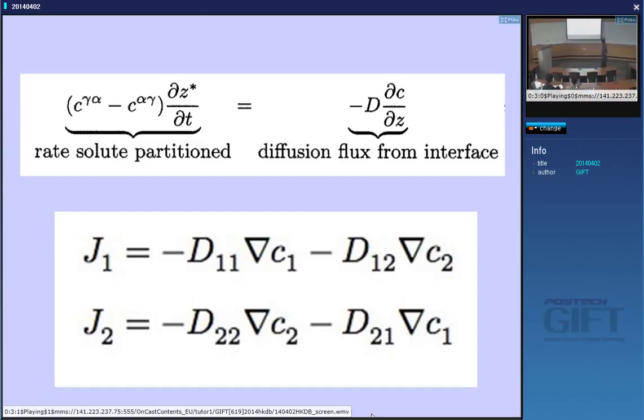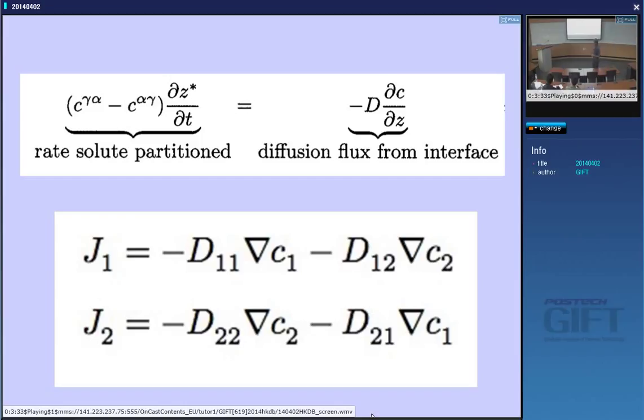The concentration terms in the phase diagram for manganese and carbon are different, but not eight orders of magnitude different. The concentrations of carbon and manganese which are in equilibrium in the phase diagram are not eight orders of magnitude different, and similarly the gradients are not that different. So we have a problem in simultaneously satisfying both equations — the mobility of carbon is so high that how is it possible for manganese and carbon to keep pace?